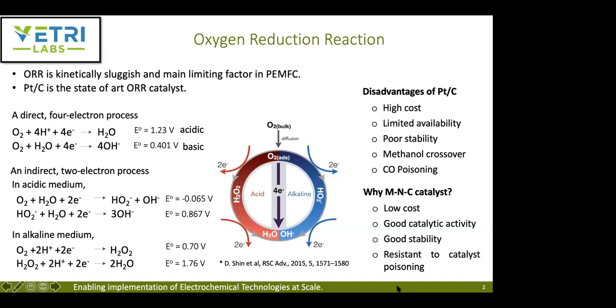To carry out the oxygen reduction reaction, platinum supported on Vulcan carbon is the state-of-the-art ORR catalyst. ORR can happen through different pathways. Ideally you want it to be more efficient, a 4-electron reduction, where oxygen gets converted into water in acidic solutions, or hydroxide ion in alkaline solutions. Or there could be an indirect 2-electron process in acidic medium, with peroxide ion formation. I actually missed this, so this should be alkaline and this should be acidic.